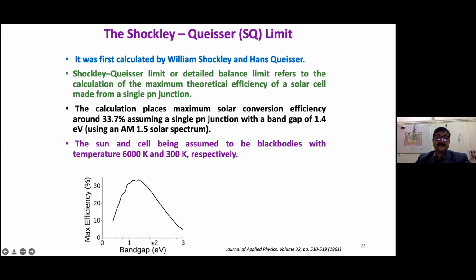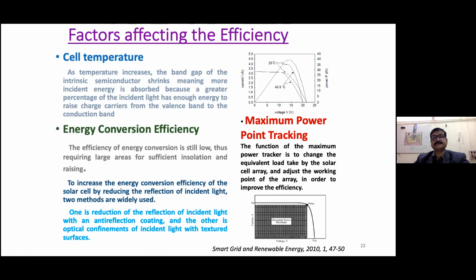The relation of the maximum efficiency with the band gap: the efficiency is maximum at about 1.4 to 1.5 electron volt. The corresponding wavelength you can always calculate by energy Eg is equal to hc by lambda, or h nu. So nu and lambda can be calculated. The factors affecting the efficiency: of course, the cell temperature, the higher the temperature, the lower the efficiency. The energy conversion efficiency depends on many parameters, such as reflection, charge carrier conversion, trapping of the light, and absorption of the light. As I said, the maximum power we have already defined, so there is no need to redefine it.